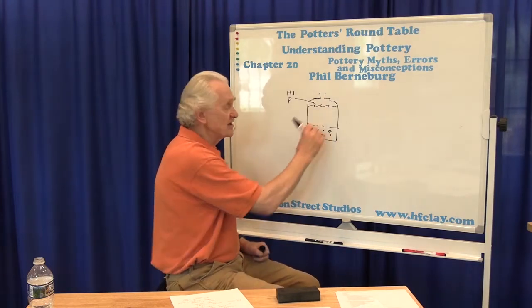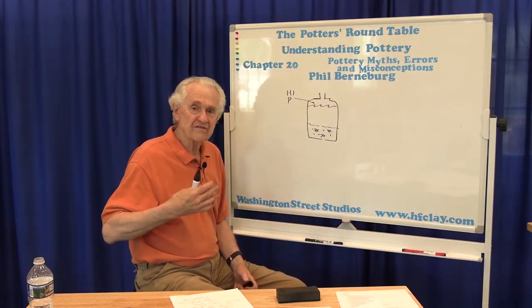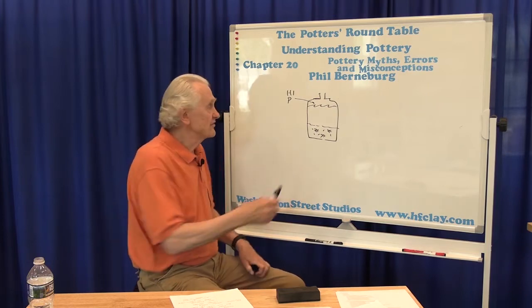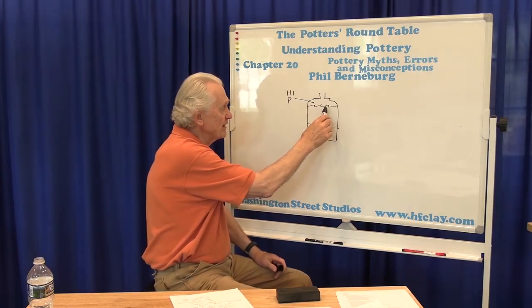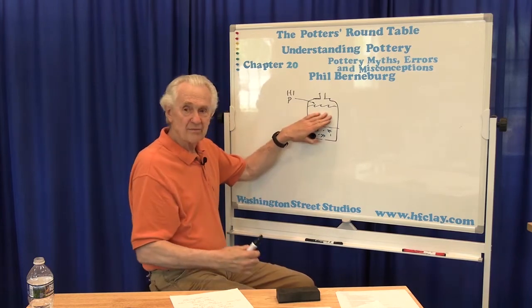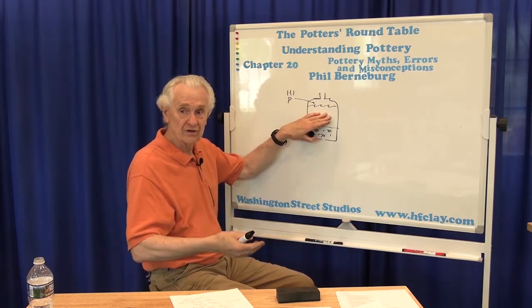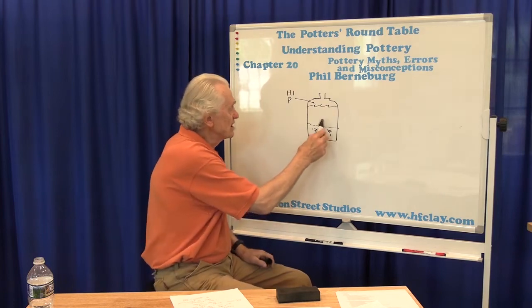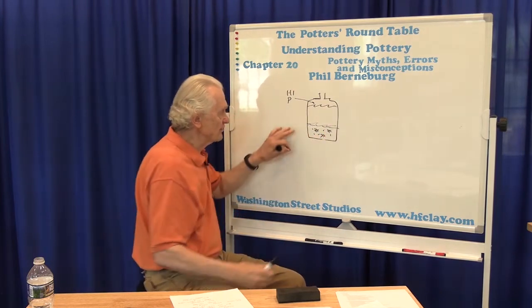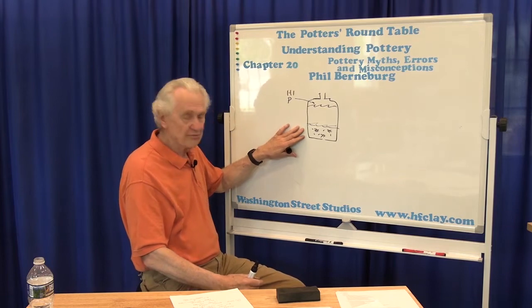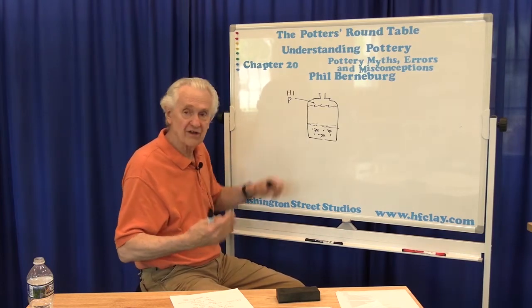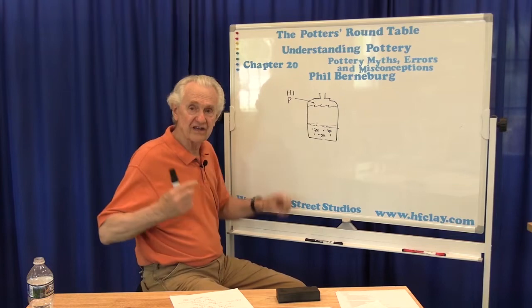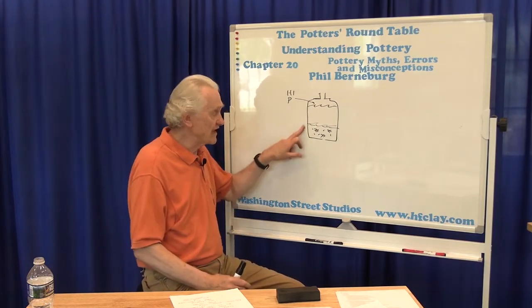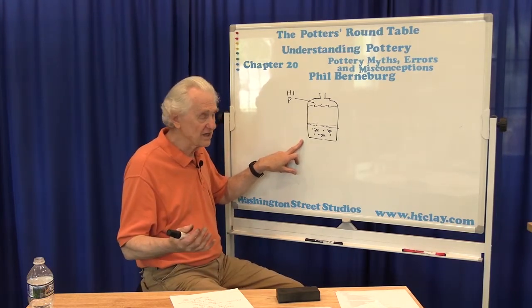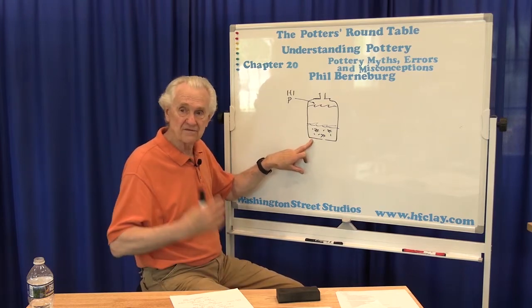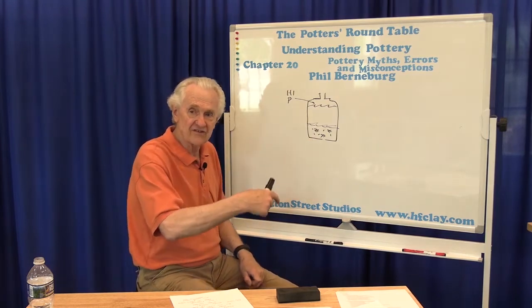So as the level drops, we know that when something evaporates, it has a cooling effect, right? So as the propane is evaporating, the liquid that's left behind is getting cooler and cooler because it's being cooled by the evaporation. Well, when the level in the tank gets low enough, and the remaining liquid propane has gotten really cold, it gets cold enough to actually condense the moisture in the air on the outside of the tank. And if it really gets cold enough, which it can if it gets low enough, it can actually freeze the water that's condensed on the outside of the tank.